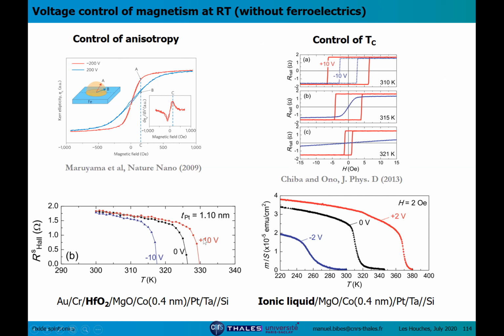And in fact, what happened is that the TC is shifted by maybe 10 or 20 Kelvin when the voltage is applied. When the ionic liquid is used, the voltage doesn't need to be so high, and the effect is much more spectacular. You can see that the shift can be up to more than 100 Kelvin. And so this is, I think, very encouraging. But because in principle, with the best ferroelectrics, you are able to accumulate or deplete charges with about the same amount as what you use with ionic liquids, in theory.